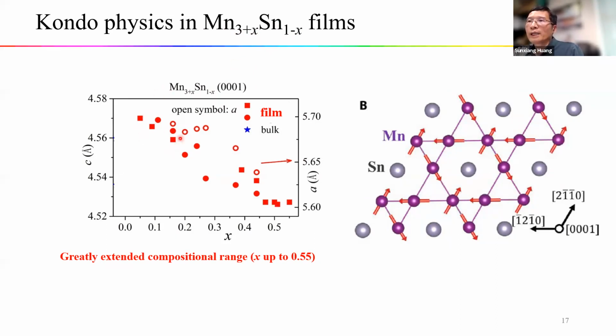So in the film, we can actually get x up to around 0.55 without introducing impurity phases. So this is much larger than previously reported in the bulk materials, in which x is only about 0.15. So in other words, we have greatly extended the compositional range that the bulk materials don't have. So roughly half of the tin atoms can be replaced by the manganese, let's say manganese impurity. So what's the new physics we may get from this extended doping?